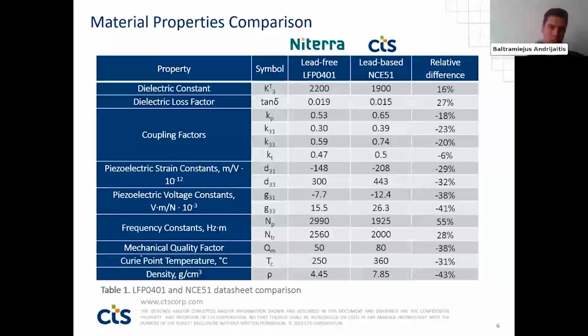The higher the dielectric constant, the higher the capacitance should be in theory. However, in general, capacitance is inversely dependent on the frequency constant, which we can see here, and the difference is quite high. So it means that the overall capacitance of lead-free material will unfortunately be lower compared to NCE51. Also, all other parameters, including density, are lower.